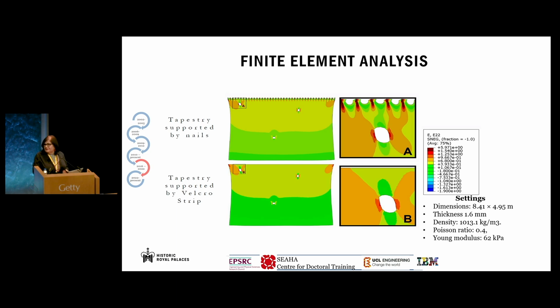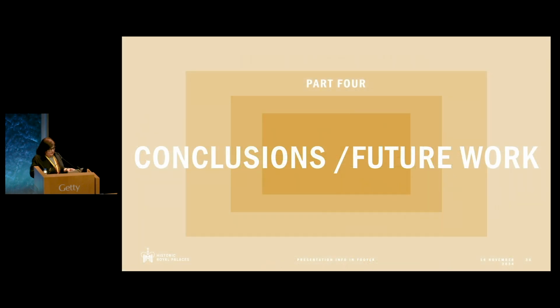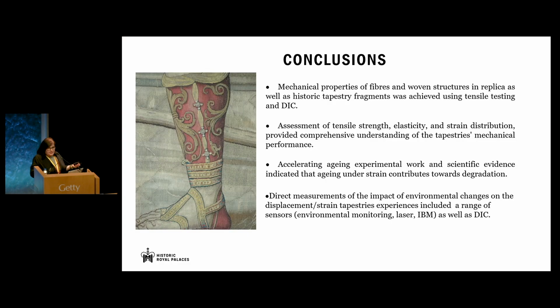So I think I need to finish. So very briefly, to sum up, one of the main outcomes of our research has been the detailed characterization of mechanical properties of replica, as well as historic tapestry samples. So that was very important for us, that we were able to incorporate some real samples in our studies. Also, the fact that we have experimental evidence that the strain the tapestries experience under their own weight contributes to the degradation.